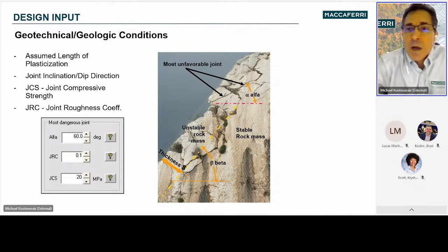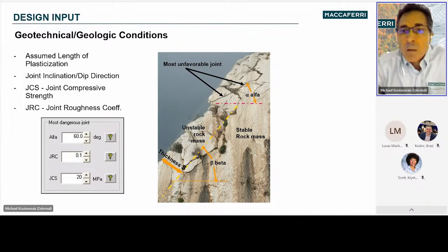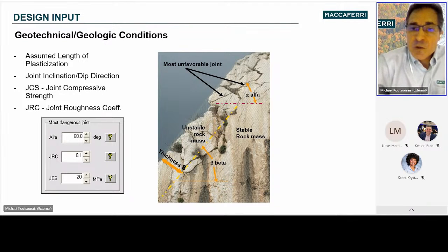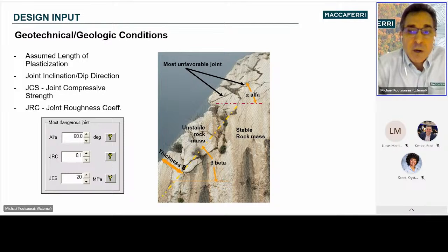Next, we'll characterize the most dangerous joint. The problem is that we have a set of joints dipping in an unfavorable way with an inclination alpha exiting through the face. There is an assumed length of plasticization based on the fragmented or weathered condition of the rock face. We assign a joint compressive strength, a JCS, and a joint roughness coefficient, JRC, to characterize the strength of this most dangerous joint.